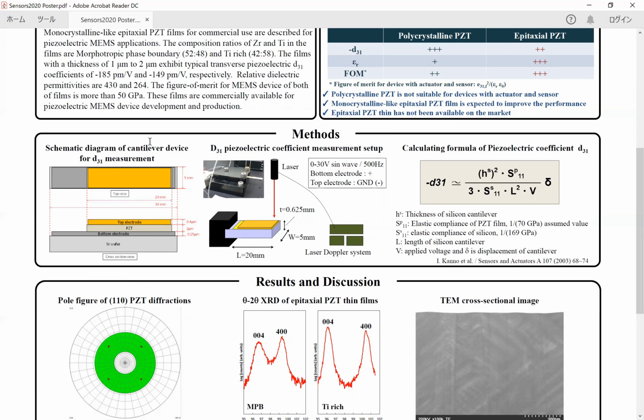Cantilevers are driven with a peak-to-peak 0 to 30 volt sine wave at 500 Hz. A DC bias of half the peak-to-peak voltage was applied to produce a unipolar drive of the capacitor. Displacement of the cantilever results from the strain induced by the converse piezoelectric effect of the thin film. The LDV system measures the displacement of the cantilever tip. From the cantilever tip displacement and dimensions and materials elastic compliance, the transverse piezoelectric coefficient D31 is calculated.